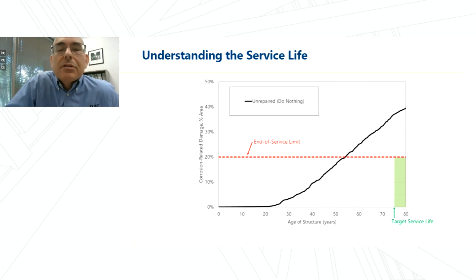You can also see that there's an initial latency period of about 20 years in which very little damage becomes visible. This is very common for concrete structures. And after this point, corrosion begins and it becomes progressively more severe. If we had selected a different controlling mechanism, say erosion or abrasion of the concrete, there may not be a latency period and the slope of the curve might be different. Or if we had selected a concrete structure with different exposure conditions than this one, the shape of the curve could be different as well. This curve just serves for our hypothetical case.